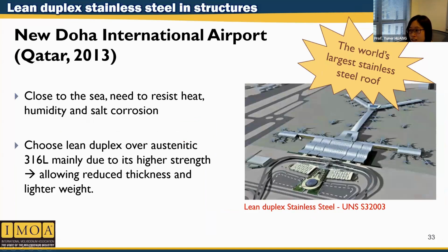And then the New Doha International Airport, they have the largest stainless steel roof. Because this airport is close to the sea and also needs to resist heat, humidity, and salt corrosion, they chose lean duplex over austenitic, mainly due to its higher strength, which also allows reduced thickness and lighter weight. So they did consider austenitic, but in the end, they chose lean duplex.